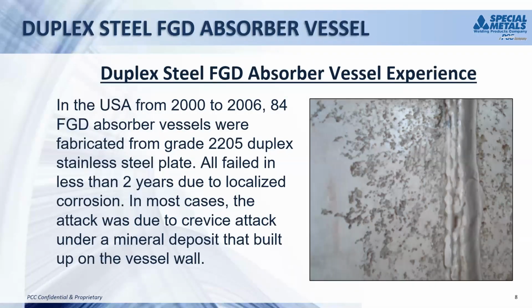The next slide shows just what happened in some operating scrubbers. Between 2000 and 2006 in the USA, there were 84 FGD absorber vessels fabricated from grade 2205 duplex stainless steel. And all of those failed by perforation, by corrosion, in less than 2 years. And in most cases, the attack was even more rapid than that. Some failed in as little as 6 months. The picture on the right shows the type of corrosion we see. The weld itself there is Inconel filler metal 625, and you can see there's no corrosion of the weld itself. But these welds are actually standing rather proud of the base metal, so they were a place for the deposits to collect. So once the deposit formed, you can see what happened underneath. There's very, very aggressive crevice corrosion. The next slide.